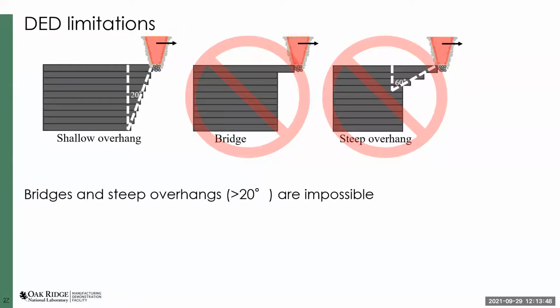But of course, I've spent just a couple of minutes talking about how DED is really great. Like any process, it has its limitations. Because DED uses a much larger bead, it's a pretty large scale metal process. I mean, you can make parts that are on the order of a meter large. It's very, very difficult to create overhangs and bridges, more so than with other processes, because the bead that you're using is much larger and much heavier. So you're really restrained in the steepness of your overhangs, the length of your bridges, and therefore in the overall possible complexity of your geometries. So the general rule of thumb is that you really can't print anything greater than 20 degrees as an overhang.